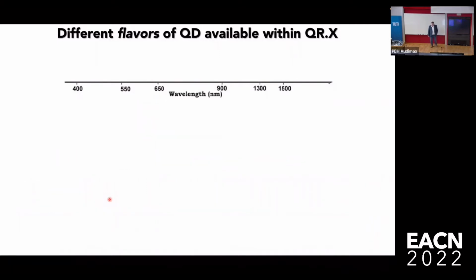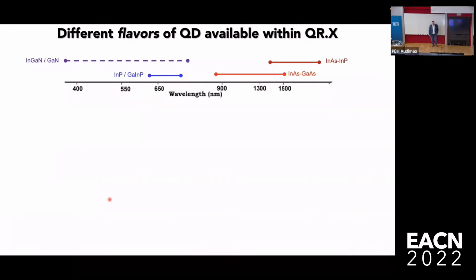So this is, if you like, the basic properties, and there are many different flavors of quantum dot available within the QR.X community. So there at the top, you see the emission wavelength, and I've marked in there the typical wavelengths where we are working. So we're working basically with different types of quantum dot systems. Indium phosphide, gallium indium phosphide, that tends to be in the visible. Going towards the telecoms range, you have quantum dots like indium arsenide on indium phosphide substrates, indium arsenide on strain release layers. You can make them emit up into the telecoms O band and into the C band. And of course, we also have, let's say, key wavelengths, silicon vacancy, maybe tin vacancy also, rubidium. And for that, there are also gallium arsenide quantum dots. So you see, at all of these key wavelengths, we can find quantum dots which can match specific target wavelengths, whether it be telecoms or specific quantum emitters.